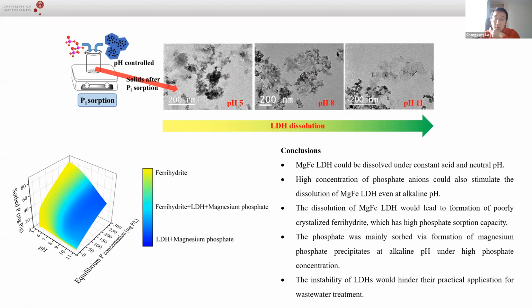As we could see, the magnesium iron LDH could be dissolved under pH neutral or weakly acidic conditions. And a high concentration of phosphate could also stimulate the dissolution of the LDH. We also found that the dissolution of the LDH could lead to the formation of an amorphous ferrihydrite phase, which also has a really high adsorption capacity for phosphate.